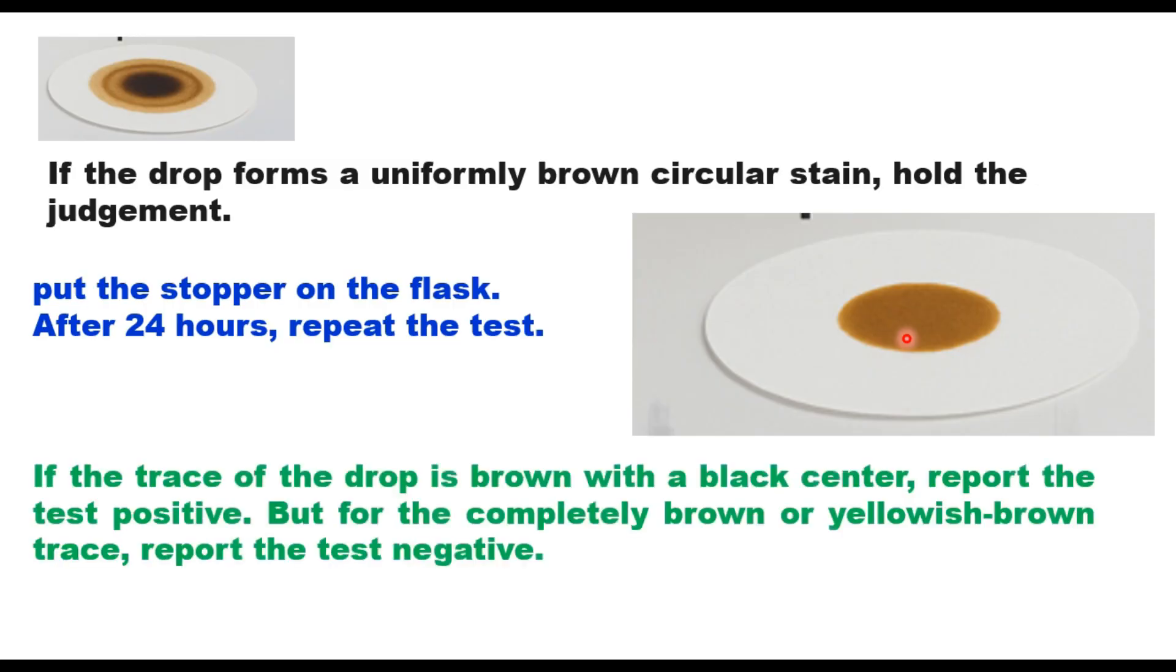If the trace of the drop is brown with black center like this, then test is reported to be positive. But if you get again the similar type of stain, that is completely brown or yellowish brown trace, then the test is negative.